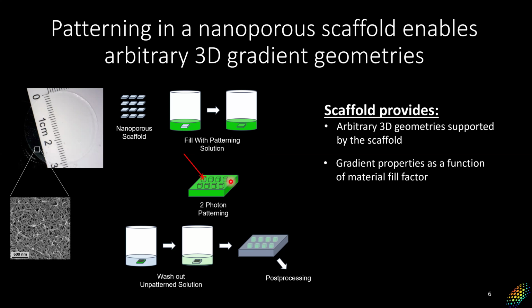And so then you end up with a nanoscale mixture of polymer, air, and silica, where on one end you have the empty scaffold here. It's about 80, 90% air, so it has an effective index very close to 1. On the other end, you can fully fill it in with polymer. This gives you an effective index close to 1.6. And then by controlling the degree of filling in, you can get essentially any index in between those extremes. And then at the end of the day, you're left with a full assembly or optical microsystem that is embedded in a monolithic structure that's mechanically robust for packaging and integration.